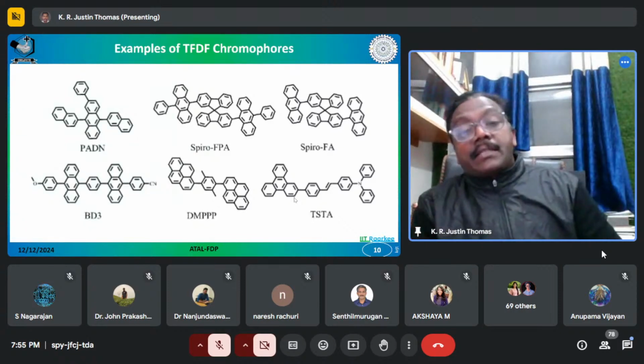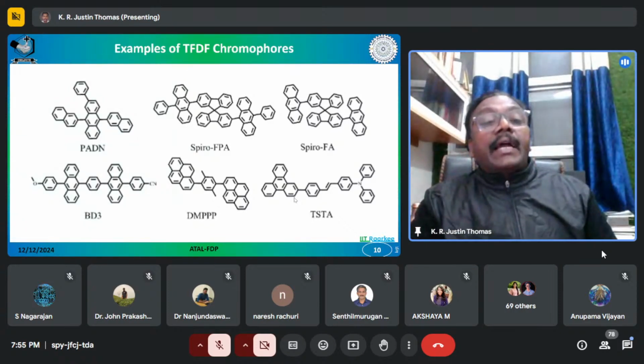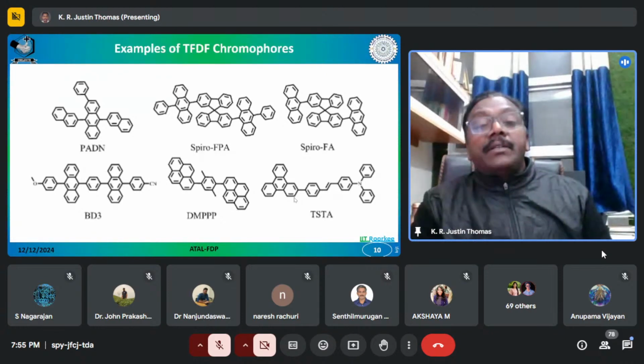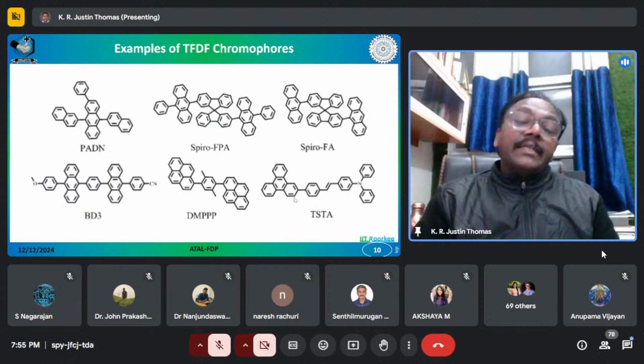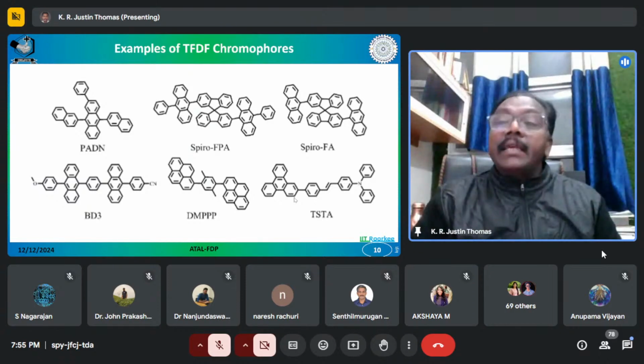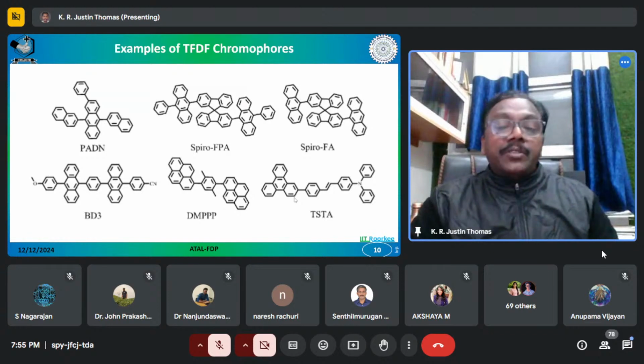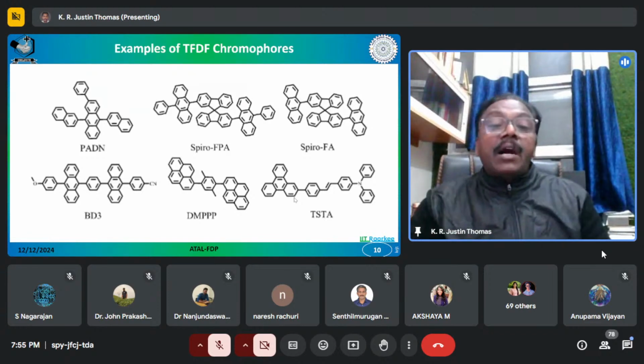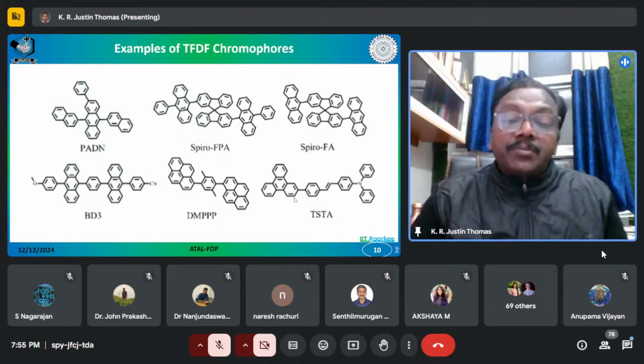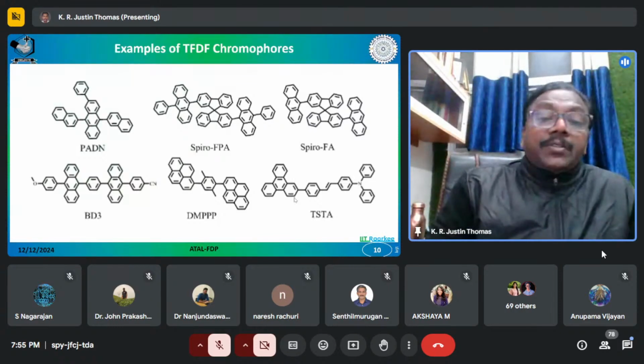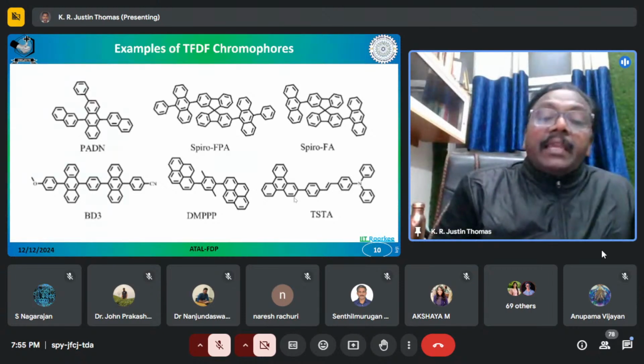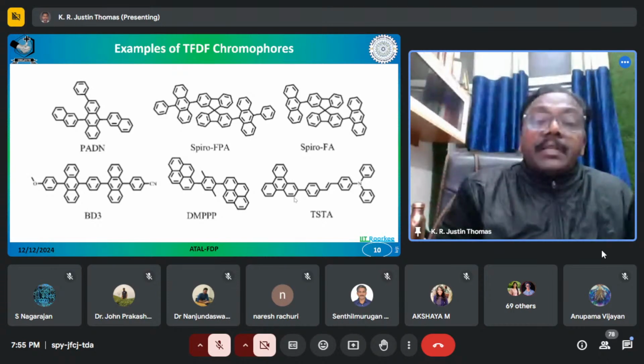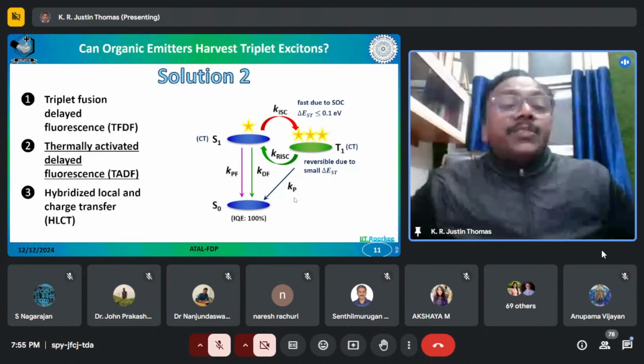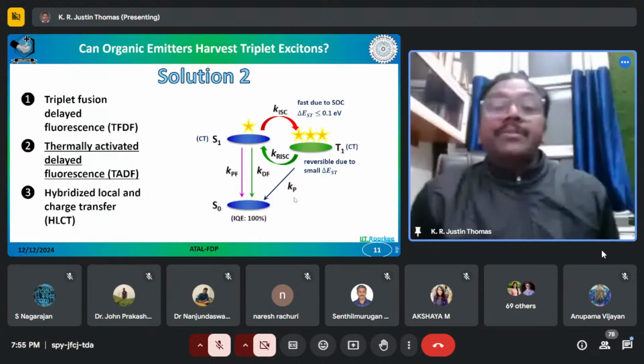Because of this, they have only a pi to pi star excitation, and their triplet excited state energy level is nearly half of the singlet excited state energy level. That is, the triplet excited state lies at nearly half the energy of the singlet excited state in these molecules. So this is only of historical importance, because there is not much room for further development of these materials due to the processability issues. And then the second solution is thermally activated delayed fluorescence.